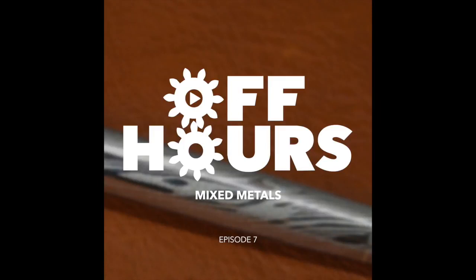So what alloys are you working with for the mokume that you've been making? There's a few different metals that I like. There's two Japanese copper alloys. One is Shibuichi and the other is Shakudo. One has a little bit of gold in it, the other has a little bit of silver in it, and they look very similar. They look like a nice pink copper when you look at them. But when you apply different patinas to them, they turn these beautiful brownish gray colors, sometimes almost a purplish color. And so they're quite striking in contrast to something like silver or gold. Also, when you combine things like palladium 500 and silver, both of them are white metals.